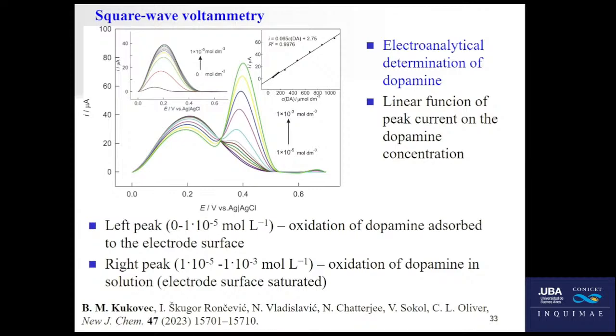So this is the square wave voltammogram. In this case, you also have various concentration regions. I wanted to say first we have two peaks in the voltammogram. The two peaks correspond to the same process, the oxidation of dopamine, but the first peak corresponds to the oxidation of the dopamine which is attached to the surface of the electrode, and the second one is the free dopamine in the solution. So how did we conclude that?